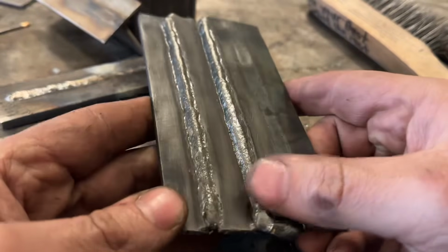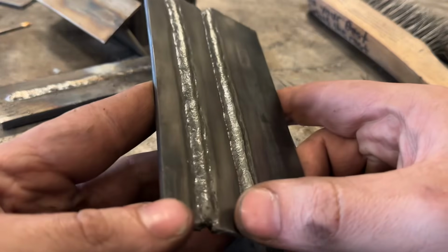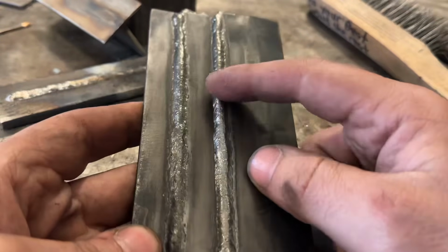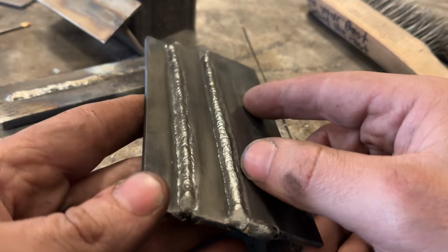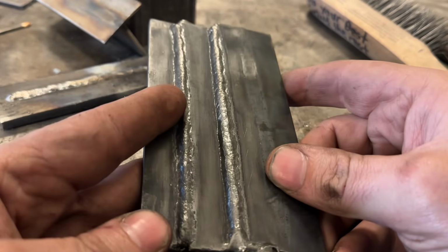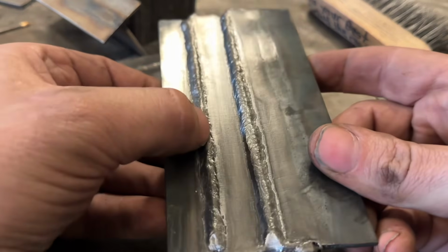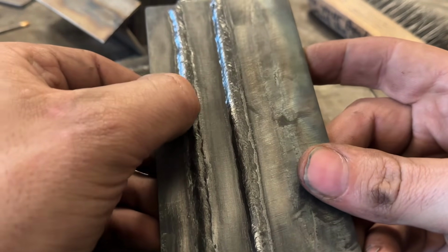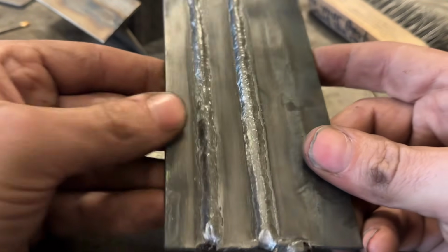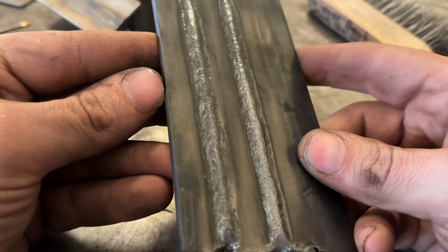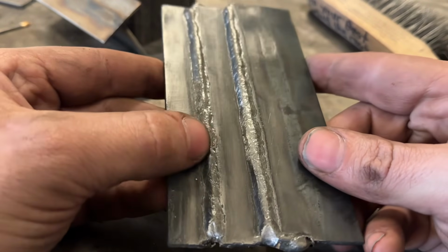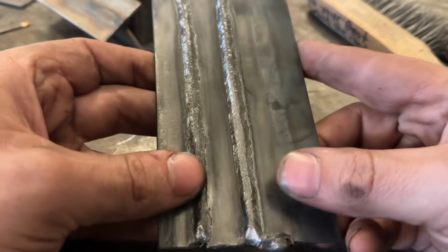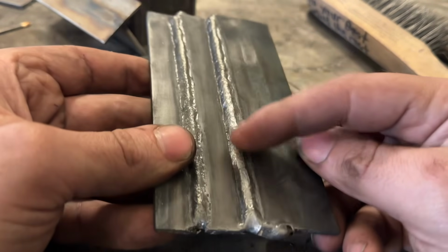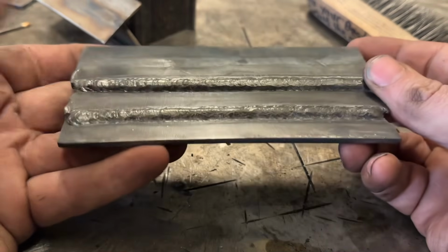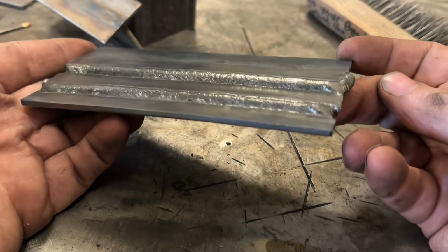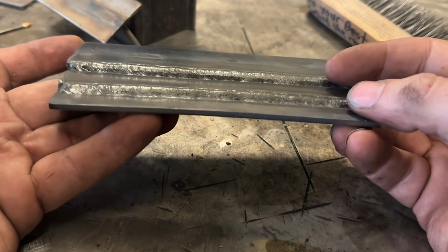So you saw me weld these continuously start to finish uphill, same as I've been doing. This one ran really good. That's looking about perfect. Doesn't really get much better than that. And then this guy, being that the plates were pretty preheated already, it looked like it was undercut. Maybe that's a little undercut, but I definitely should have waited for it to cool down. You can see how preheated plates can make a difference. Not having a camera in your face also helps, so it made it a lot easier to weld that uphill. You can see the lower toe line is nice and clean and crisp.